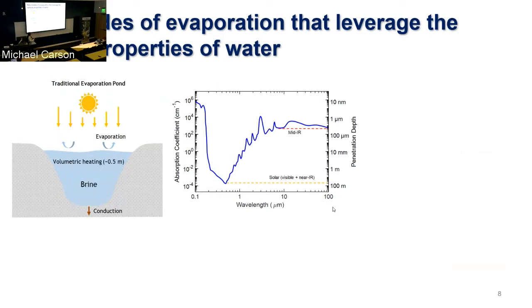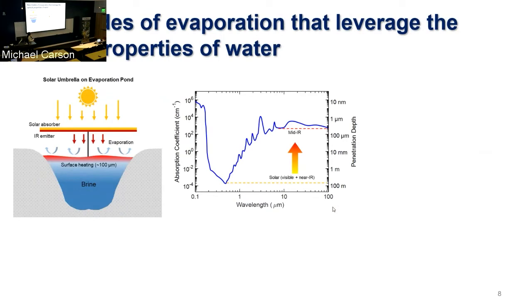But what we see is that water really becomes a good absorber in the mid-infrared. So what if we took the sunlight, converted it into different wavelengths in the mid-infrared, and that way water would inherently very strongly absorb the incoming radiation and keep it all at the surface. You no longer need that insulating foam or the capillary wicking. So here we look at transforming the solar into the mid-infrared using these photothermal converters. These are selective solar absorbers and selective emitters that are designed essentially using these coating processes in order to get conversion from the primarily visible solar into the mid-infrared.